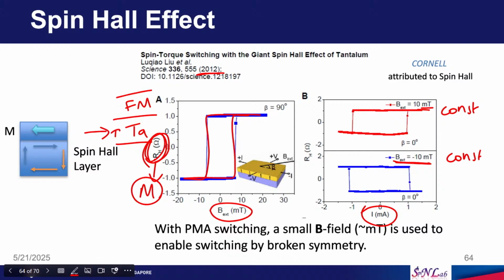Okay. So, they send current through the tantalum layer, and because of this current they see switching. Magnetization is initially in this direction. So, at some current it switches to another, let us say magnetization is like this or like this. Then again when they sweep the current, they see the magnetization going from that direction to this direction. So, they can see the magnetization switching just by sending current through the tantalum layer.